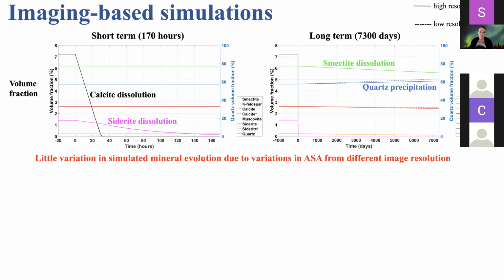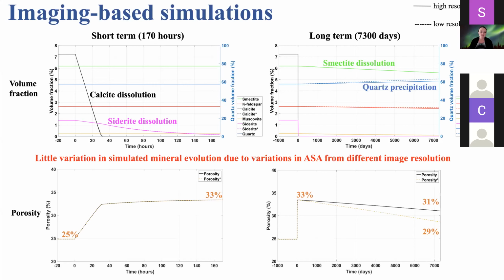What about the evolution of porosity? So here we have porosity evolution, and you can see a rapid increase in porosity due to dissolution of the carbonate mineral phases at early times, but there's very little variation in the simulated results between the two surface areas. At longer times, we start to have an eventual decrease in porosity due to quartz precipitation, and you get some slight variation in the evolution of porosity depending on surface area.